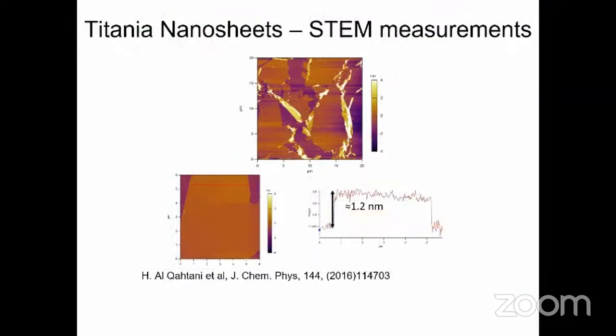And we move to the STEM, scanning transmission electron microscope. First, we deposit them on oxide, as I mentioned, to increase the catalytic activities of our gold nanocluster. We start with the unique titanate nanosheet, which is special for the NIMS Institute, where we have just a single layer of the nanosheet with a huge wide range, and we deposit our gold cluster. The thickness is just 1.2 nanometer of this sheet exactly.